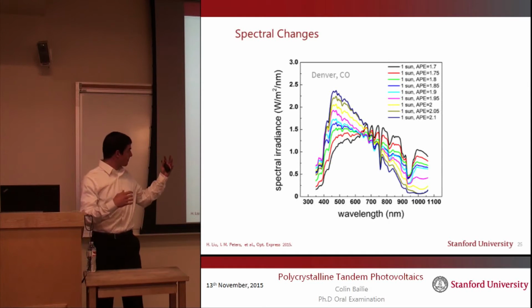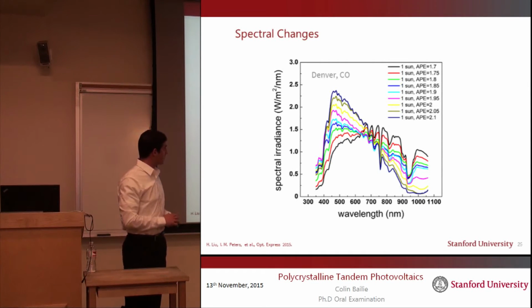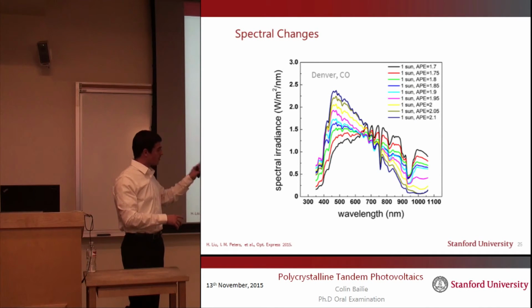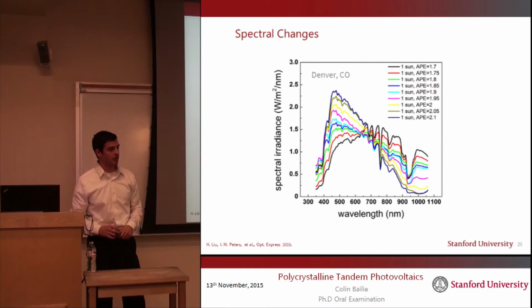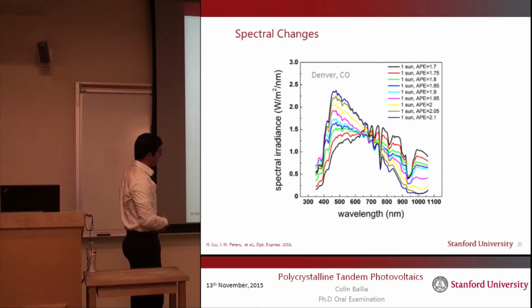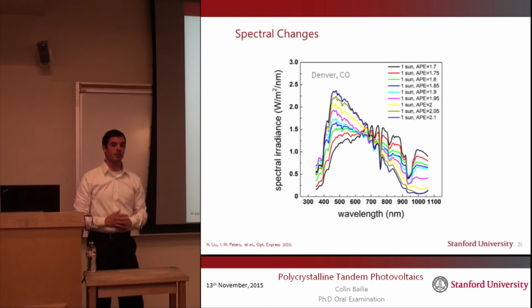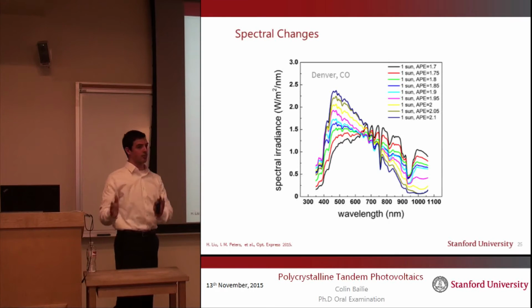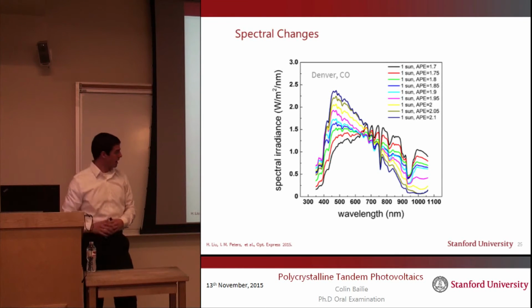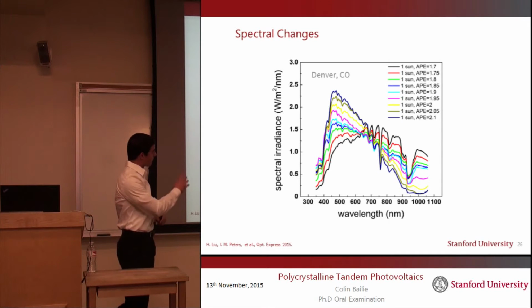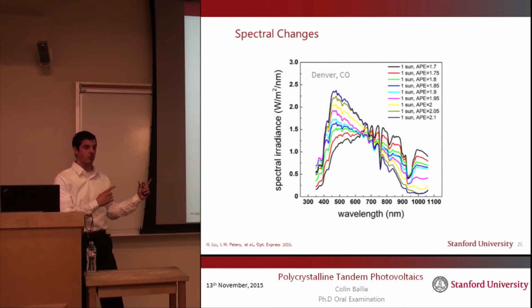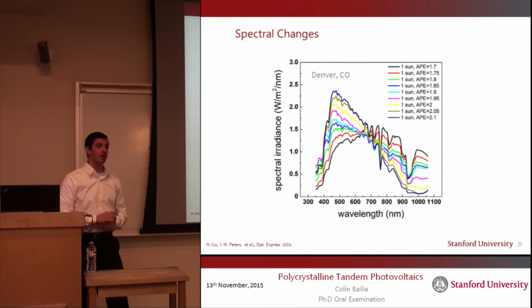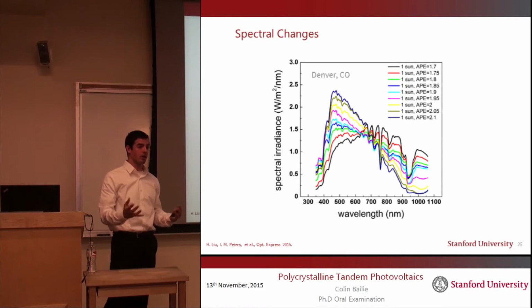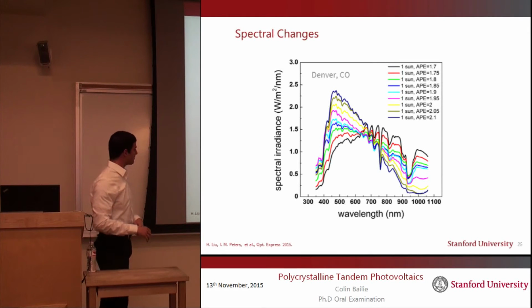And the consequence of this can be seen in this plot of representative solar spectra in Denver, Colorado, where you can split this plot in the middle at 700 nanometers, where everything to the left of 700 nanometers is what the perovskite absorbs, and everything to the right is what the silicon absorbs. And there's some cases here where the perovskite and the silicon will absorb about the same amount of light. But there's also a lot of situations here where that is not the case, and there will be a current mismatch between one or the other absorbers.